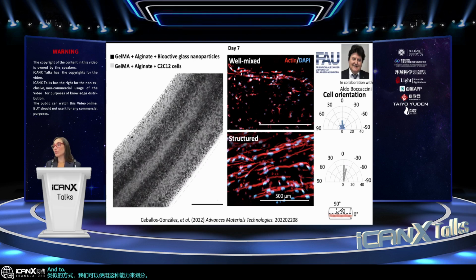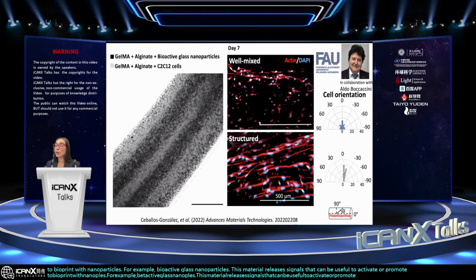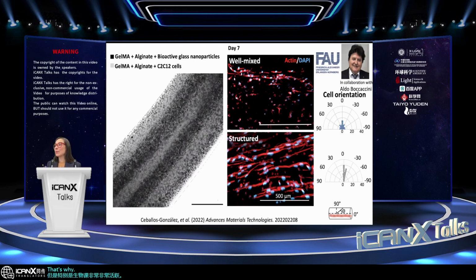In a very similar way, we can use this ability to compartmentalize to bioprint with nanoparticles, for example, bioactive glass nanoparticles. This material releases ions that can be useful to activate or promote certain cell processes, but bioglass in particular is very, very active, so it can be aggressive to cells. That's why we wanted to have them close to cells, but not scrambled with cells. So we printed fibers with intercalated layers of cells and bioglass. So it was cells, bioglass, cells, bioglass, in separate layers.